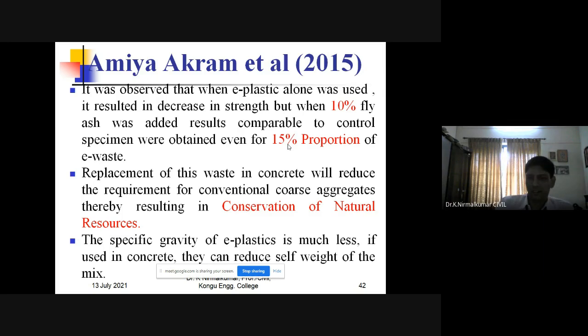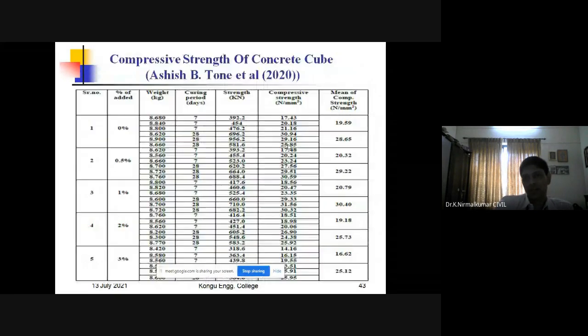So to counteract this, we have to go for some research work to determine a proper dosage of admixture or a proper chemical to improve the specific gravity and to have a counteraction. As far as this 15 or 20% is considered, it is good. Moreover, they had added fly ash. Fly ash is also a good pozzolanic material, and it may be one of the reasons for the little bit better strength.